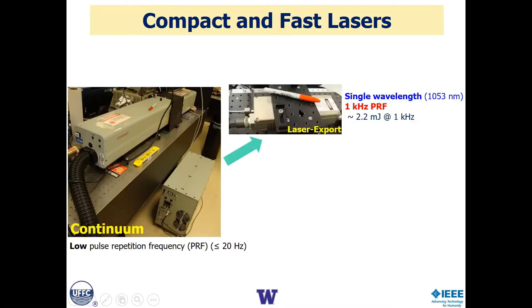This is a diode-pumped solid state laser. It's a YLF, which is the laser material, so it's 1053. It works above a kilohertz PRF. We typically run it between 1 and 10 kilohertz PRF and it has single digit millijoule energy. However, in our delivery system, the fluence at the tip of an individual fiber is the same for this system as it is for this system. Only here, we're delivering all the light only to one fiber at a time.